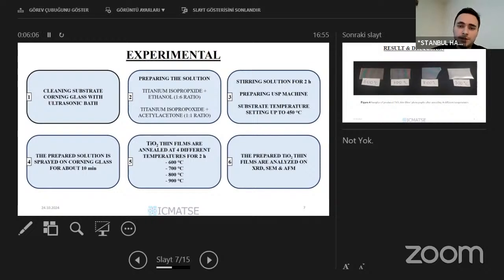we stir the solution for about 2 hours. While this stirring happens, we should prepare our USP machine — putting our cleaned glass on the heating plate and setting up the substrate temperature to 450 degrees so our glasses get heated.